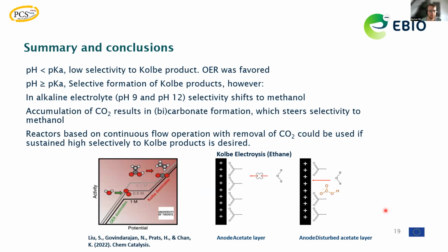So with this, I'd like to conclude this talk on Kolbe oxidation. And I think the key take-home message here is that we have possibilities to selectively tune Kolbe processes to either the Kolbe product or the non-Kolbe product. And this would, of course, be of great relevance if you want to operate this in continuous flow and make use of the bioliquid in the end, and basically design a process where we can decide if we want to form a gas phase product to stabilize our oil, or if we want to even go for an alcohol, which might even increase the energy density of the pyrolysis liquid.